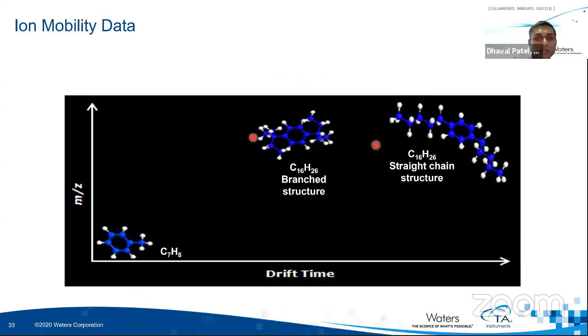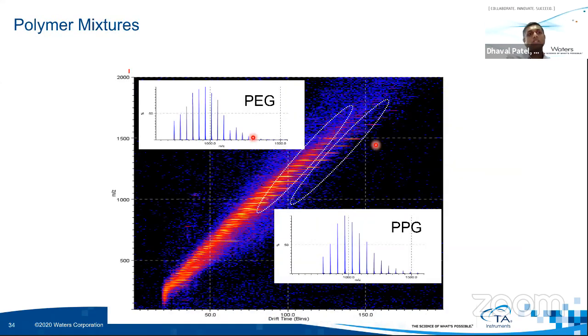So in this case, I have a mixture of PEG and PPG, two different polymers. If you mix them together, it's very difficult to separate this polymeric mixture by any other technique. But when you run this with ion mobility mass spectrometry, this data represents the molecular weight of your polymer, and here is the drift time, or the time when it comes out from the ion mobility. By looking at this distinct pattern, we can differentiate these PEG and PPG molecules.